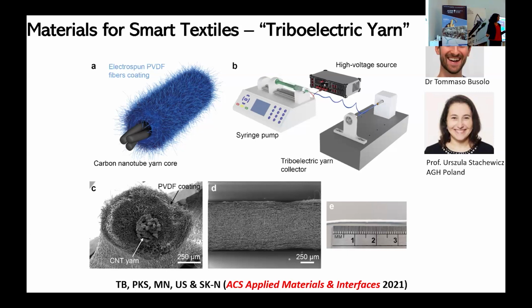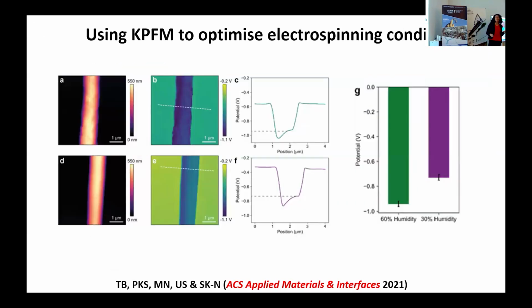So we call them textiles, but not quite there. But again, you can use things like KPFM. In this case, previously we used PFM to optimize condition. Here we're using Kelvin probe force microscopy to optimize condition. So these are basically different fibers which are grown under different humidity conditions. And you can see that one gives you a much higher surface potential. So that's the one we want for our triboelectric devices.